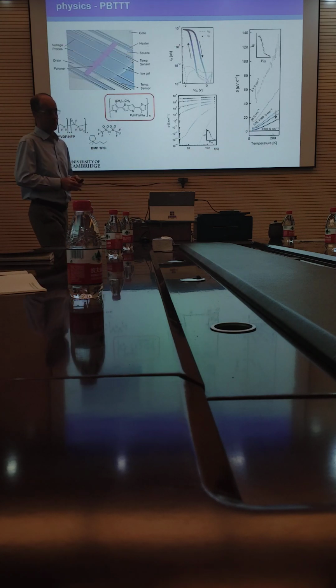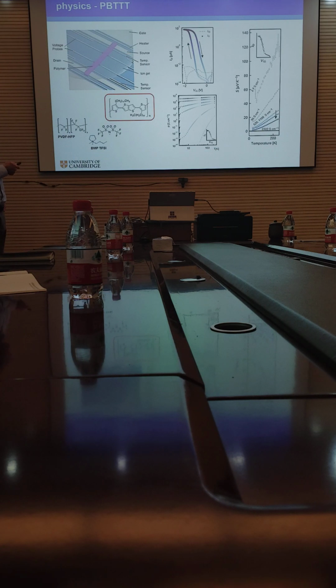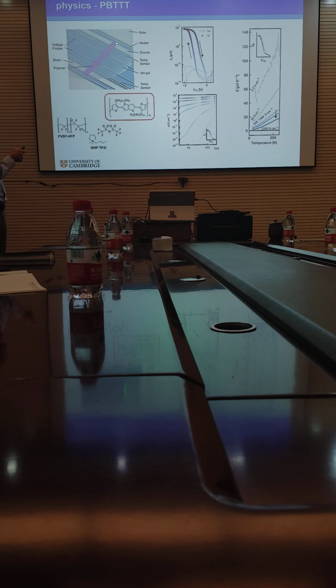This is an example. I've talked about PBTTT. Here is a PBTTT OECT. We make them with an ionic liquid-based electrolyte. PVDF-HFP is the scaffold polymer, and then we mix in the ionic liquid. You can see here the device structure. This purple region is the active layer of PBTTT. It's patterned into this elongated shape, and it's in contact with lots of different electrodes. We need these electrodes to measure the different transport coefficients: the Seebeck coefficient, the Hall effect, the magnetoresistance, the four-point conductivity. We can measure all of that in this device.